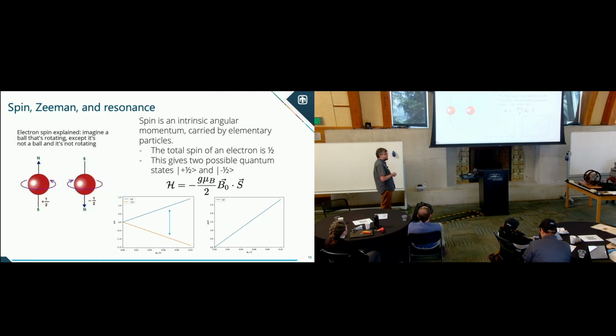All right, this is your magnetic resonance, and that difference in energy as a function of magnetic field just gives you a nice straight line, which is about 28 gigahertz per Tesla for a standard g equals 2 electron, which is pretty relevant for electrons in diamond. All right, so 28 gigahertz per Tesla. But the NV is actually more complicated than that.